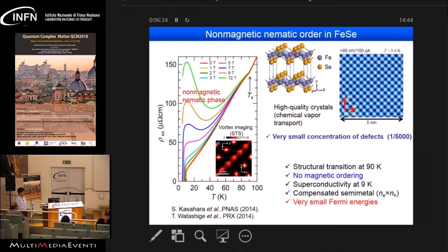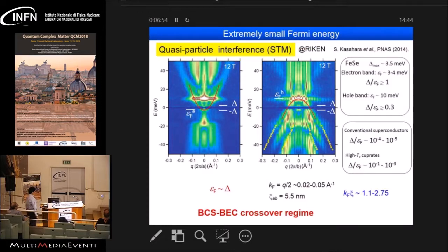If you look at the electronic structure, it has a very interesting feature. We have a compensated semi-metallic electronic structure, which means you have equal numbers of electron and hole carriers, and very small Fermi energies. That is the key to the BCS-BEC crossover. The electronic structure can be investigated by quasi-particle interference using the STM technique, which has a very high energy resolution. Depending on the q direction, we can see an electron-like dispersion like this, or a hole-like dispersion like this, from which we can estimate the Fermi energies of the electron and hole bands. At the same time, this technique can give you information about the superconducting gap delta. So we can get the delta over EF for these two bands.